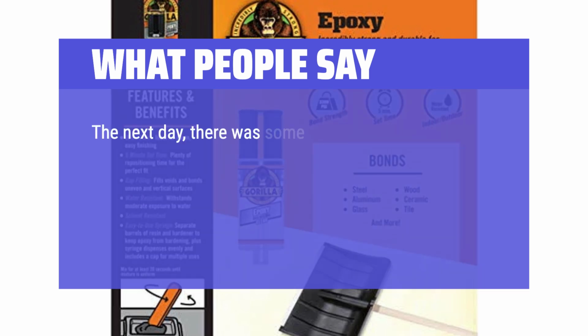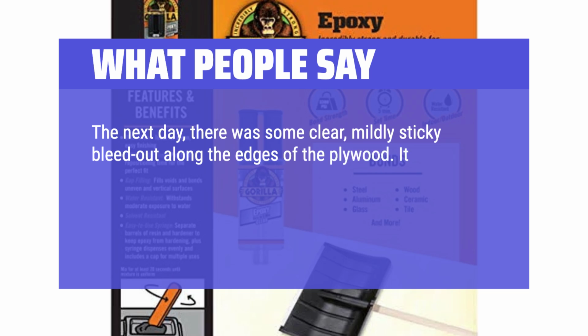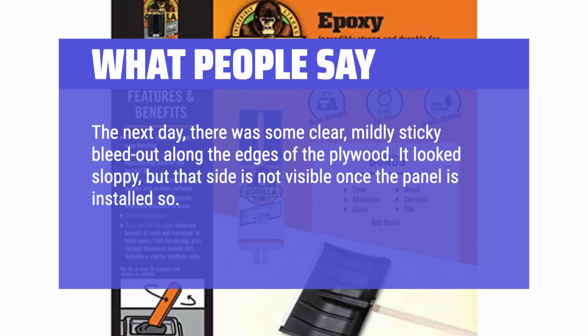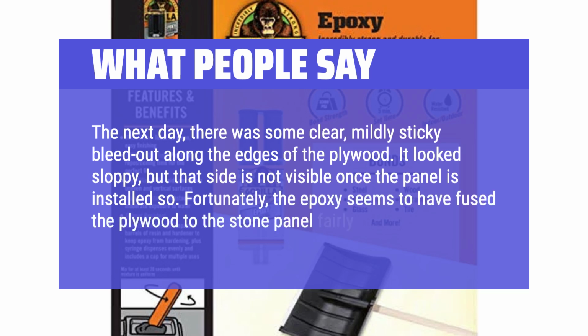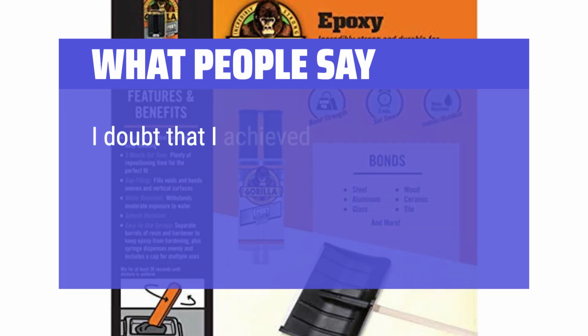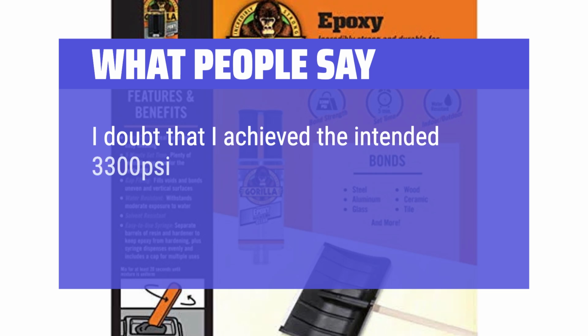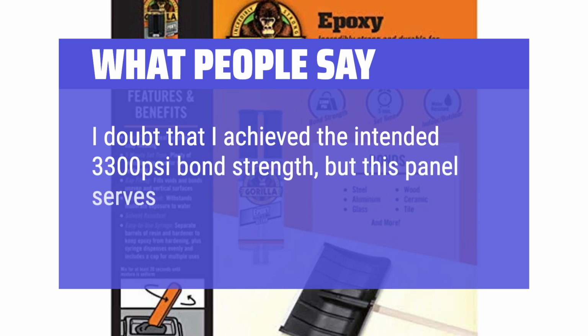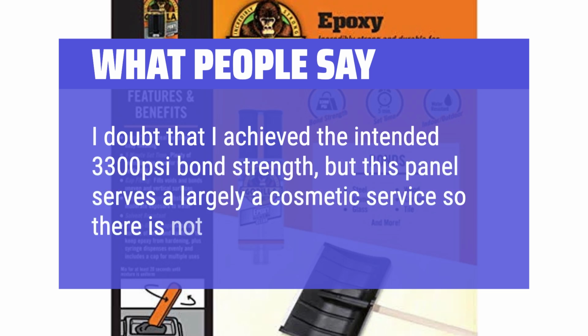The next day, there was some clear, mildly sticky bleed out along the edges of the plywood. It looked sloppy, but that side is not visible once the panel is installed. Fortunately, the epoxy seems to have fused the plywood to the stone panel fairly well. I doubt that I achieved the intended 3,300 psi bond strength, but this panel serves largely a cosmetic service, so there is not really much load on it.